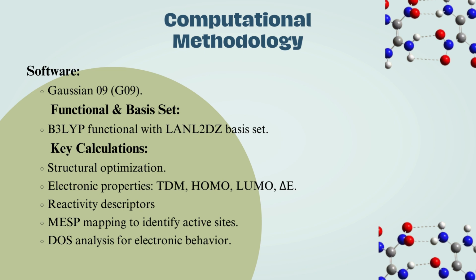B3LYP functional and LANL2DZ basis set were used based on their good combination of accuracy and computational cost. Geometry optimization as well as key physical parameters were calculated, including total dipole moment, HOMO-LUMO energy gap, global reactivity descriptors, molecular electrostatic potential, and density of states.